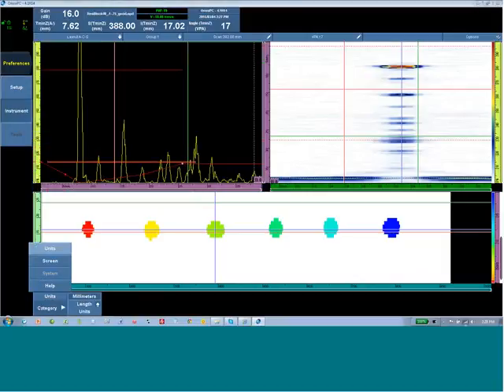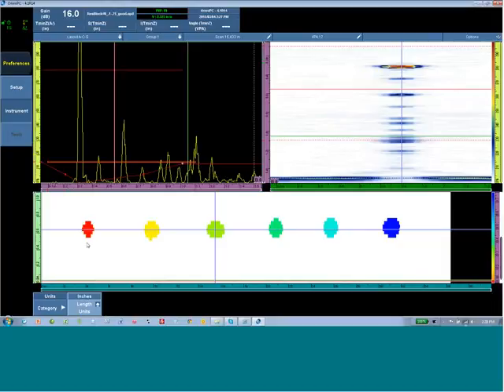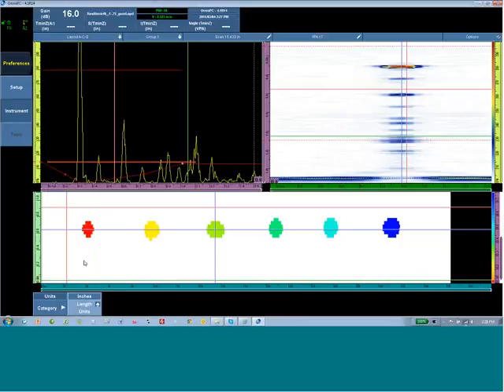So this is a unit in inches. This calibration block is set up for inches for a 0.2, 0.3, 0.4, 0.5, and 0.75 flat-bottomed hole. If we set the reference and data cursor...